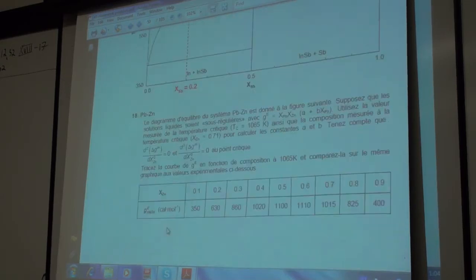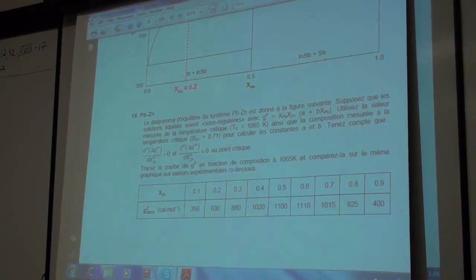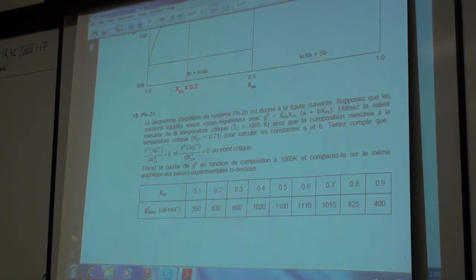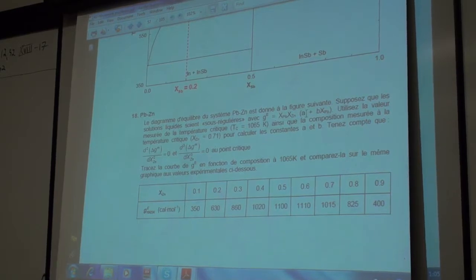So I ask you then to find the excess Gibbs energy. We haven't talked about this formally, but it is a subregular solution. The excess Gibbs energy, if you had one term, it would be regular, but clearly since the miscibility gap doesn't have a peak at 50%, it must be at least subregular. So let's put in two parameters, and the total Gibbs GXS of course is going to be positive, as you know, to give a miscibility gap.